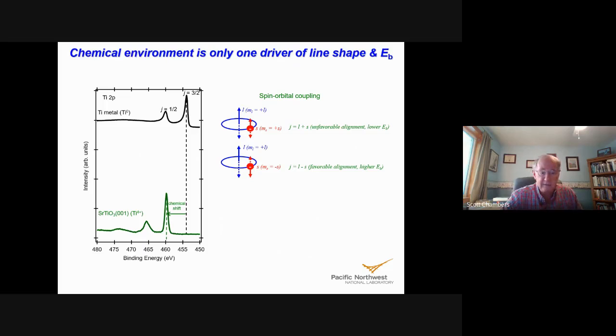But now let's take a look at a couple of other spectra. Let's take a look at that one and that one. And I'm not going to tell you what they're from at first. If you were doing surface analysis and somebody asked you to analyze their material and they showed you these spectra, or you measured these spectra, what a lot of people would do is say, oh my goodness, there's all kinds of titanium valences there. Maybe we could fit it to a mixture of titanium 1, 2, 3, 4, and maybe even titanium 5. Who knows? And in this one, maybe it's a mixture of titanium 2, 3, and 4.